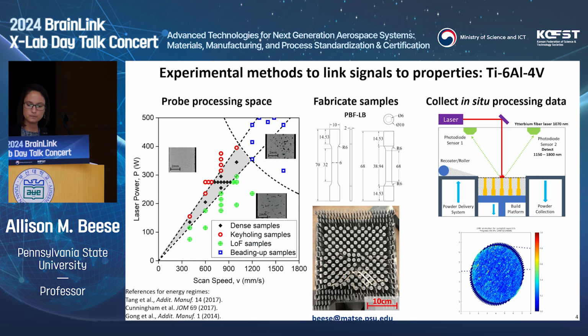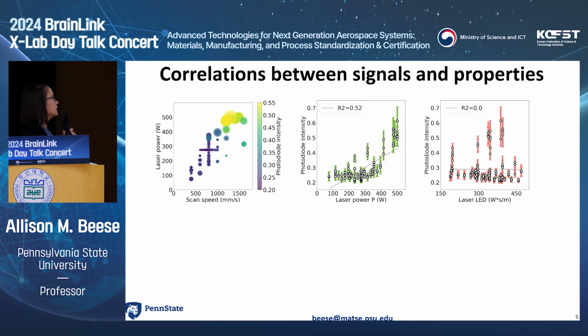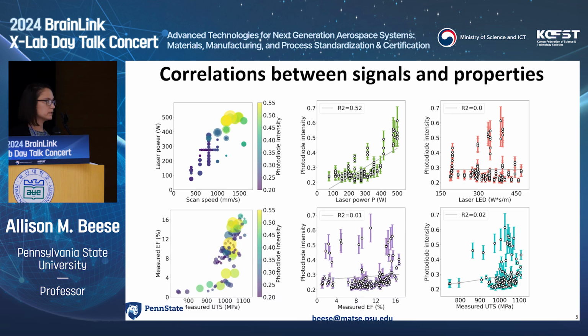And so just as sort of a baseline, if we take a look at our laser power versus scan speed for photodiode intensity, we can start to see that as we increase our laser power, of course, our photodiode intensity increases. That's represented by the colors in the top left plot. The size of those represents the standard deviation as you go through the different layers during processing. And the idea here is that if we try to correlate just the photodiode intensity itself with the ductility, which is the vertical axis on the left here, or the ultimate tensile strength, which is the horizontal axis, we don't see a correlation between photodiode signal intensity and the properties, which we didn't expect to see, but we wanted to check that first. So now what we want to do is analyze those signals a little differently.